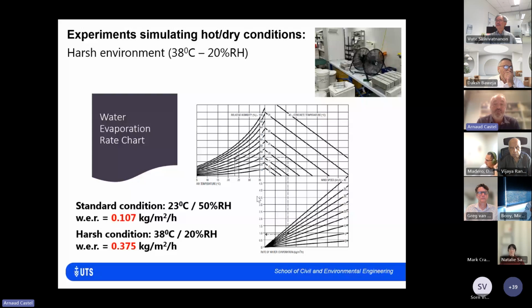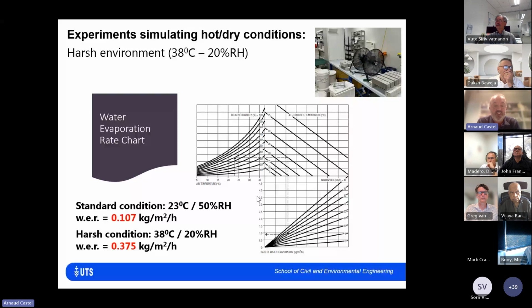A good way to assess how severe the exposure condition is, is the water evaporation rate. Everybody knows this chart. So the water evaporation rate for standard conditions, we tried to assess as well the effect of the wind speed, but I won't talk about that today. You see the fans here. So here there's no wind at all included. If we compare the water evaporation rate at 38 and 23 degrees, it's roughly almost 4 times more. So the question is, how does that influence shrinkage?